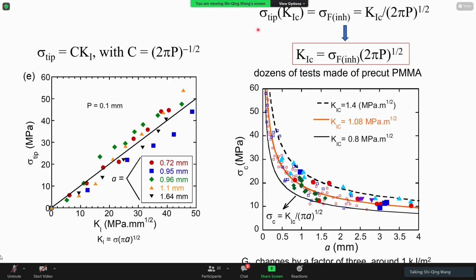Okay, and the inherent strength, what we know through nominal stress, we can measure it, and we have computed, right? In my JCP paper 2014, I have a rough idea of what that should be. It's not 17 gigapascal. I convinced myself. So in any case, moreover, this is Barry's plot. And Barry's plot, as well as our data, which is in solid symbols, show a big spread, indicating Kc has a range of more than 50%, which amounts to Gc having a range of 3 because they are square root related, or quadratically related, if you like.